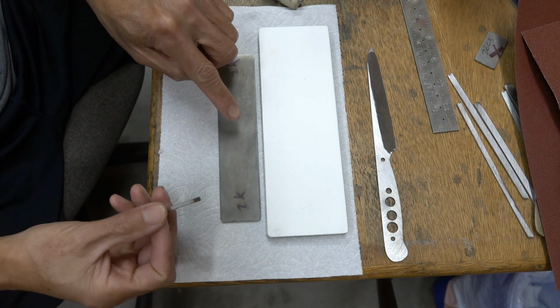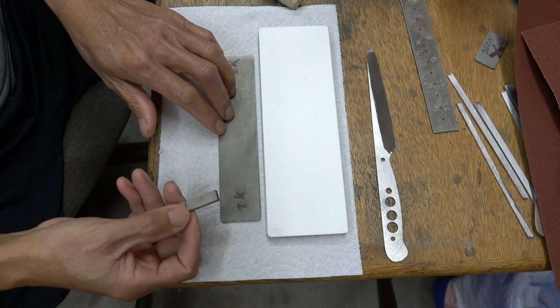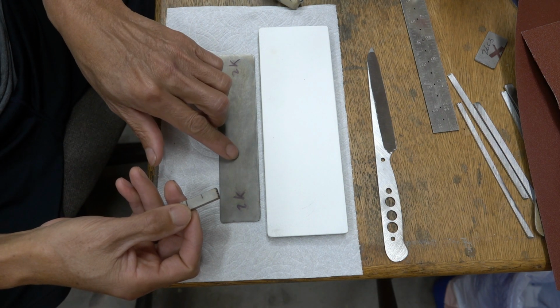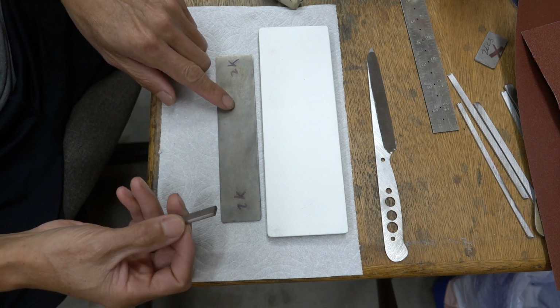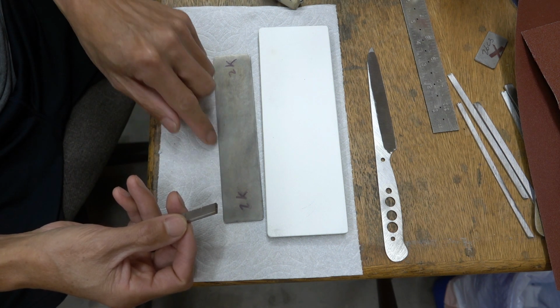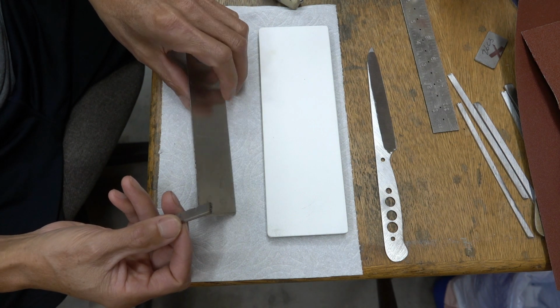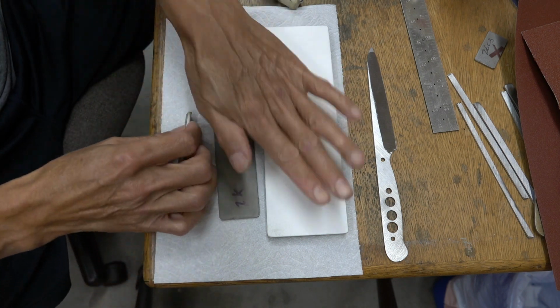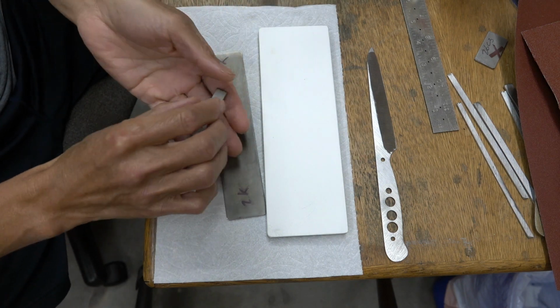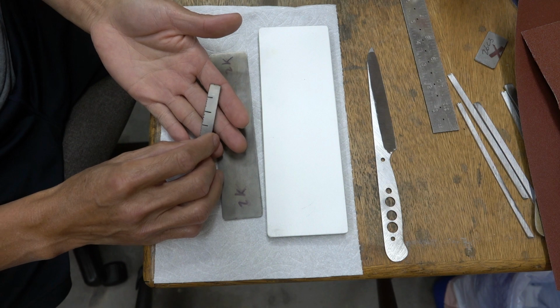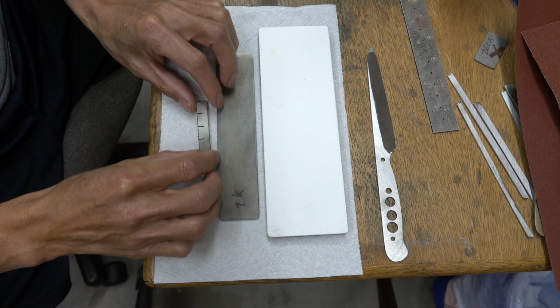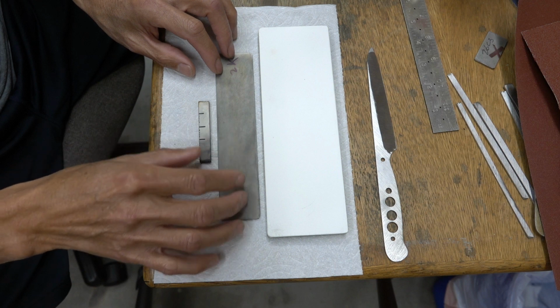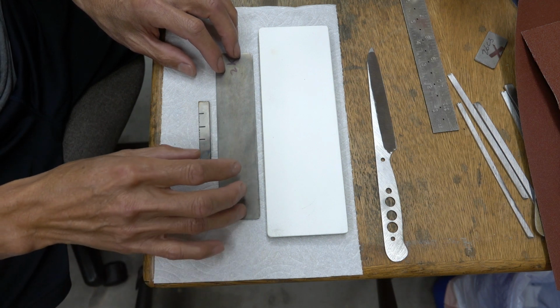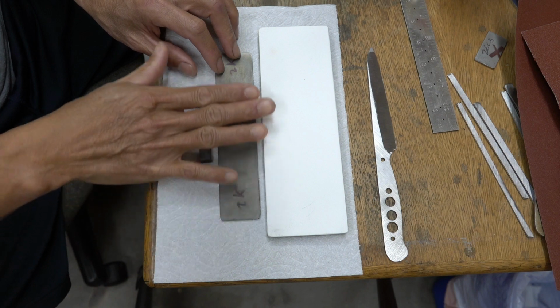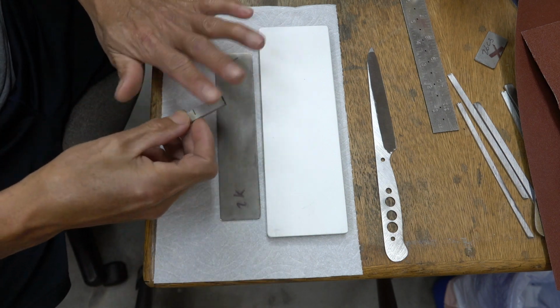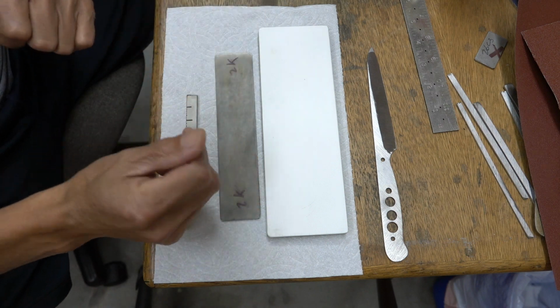For polishing, you go on the belt grinder all the way to 800 grit, and after that they get flattened and pretty much almost to a mirror with 2K. This is a diamond plate, and so the surface became flat. For steel with carbide, carbide is mostly harder than many other abrasives. Diamond and CBN are harder, so they can flatten the surface out, and that's why the surface is now more reflective and looks shiny.